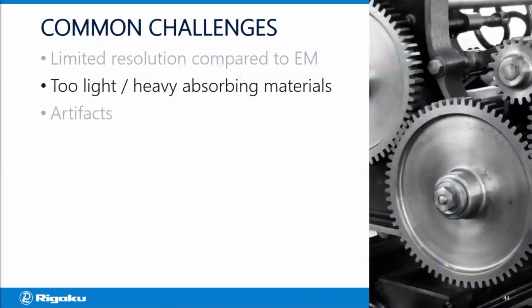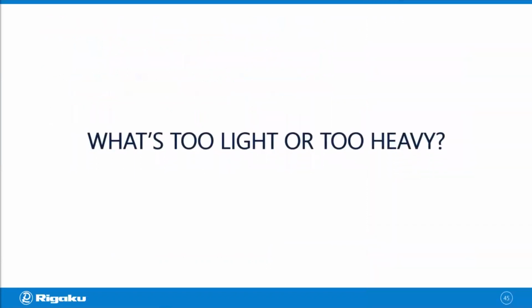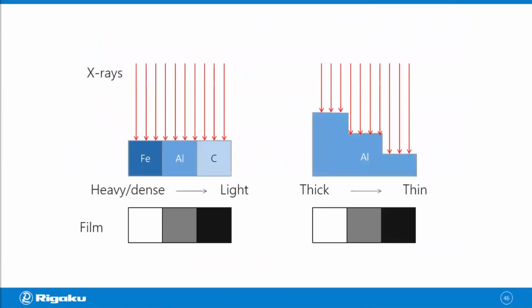The next one is too light or too heavy absorbing materials. So what is too light or too heavy? We looked at this slide at the beginning and learned that the X-ray absorption rate is density and thickness dependent. What I didn't mention then is that the X-ray absorption rate is also X-ray energy dependent. Higher energy X-rays are absorbed less by the same material.